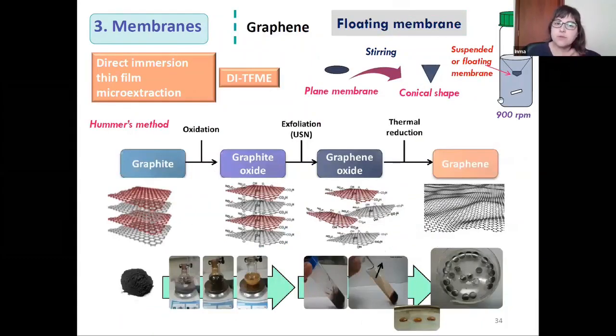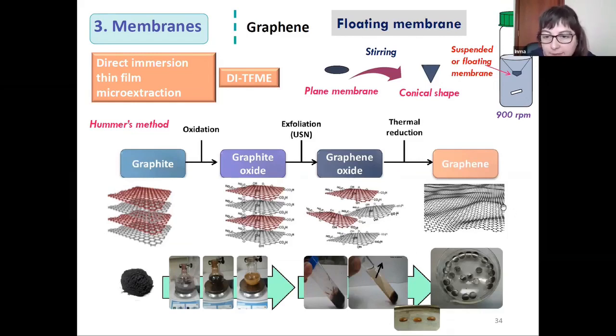Another work we performed was in relation with graphene membranes. We prepared these membranes based on the Hummers method. As we can see in the slide, we begin with the graphite powder, which is then oxidized to graphite oxide, and then it is exfoliated by ultrasound energy to graphene oxide, and finally it is thermally reduced to obtain graphene.